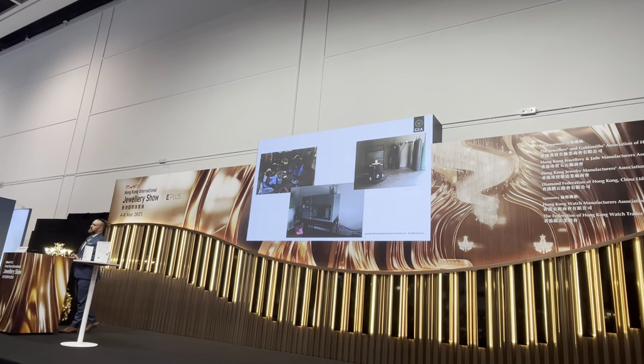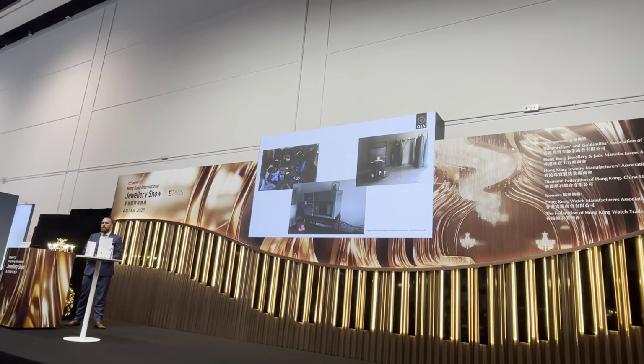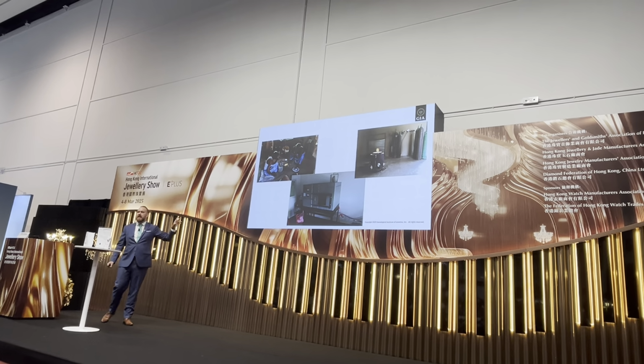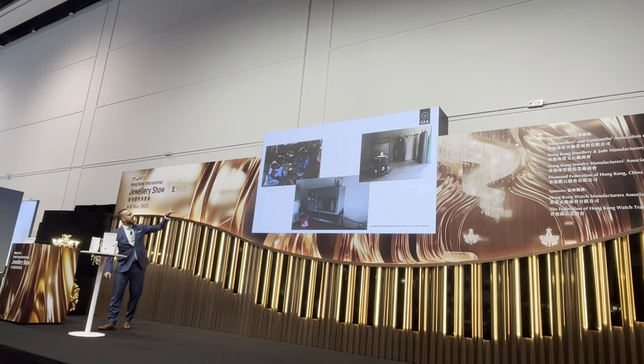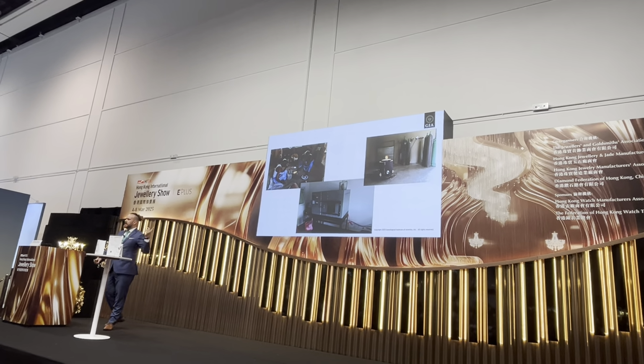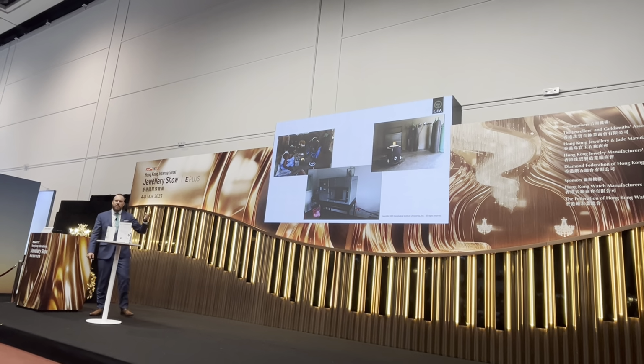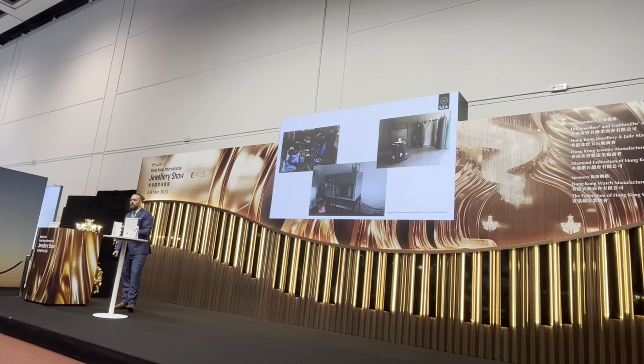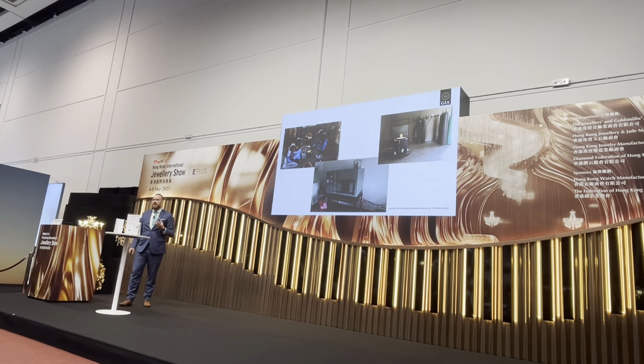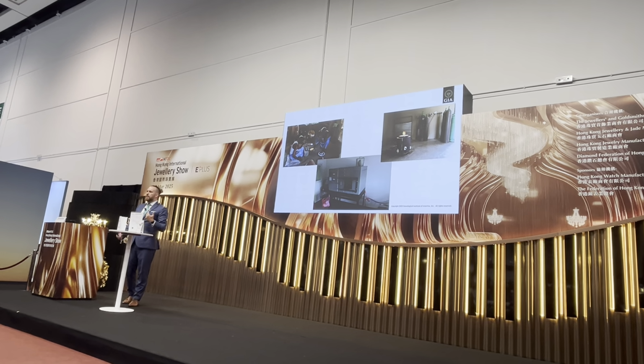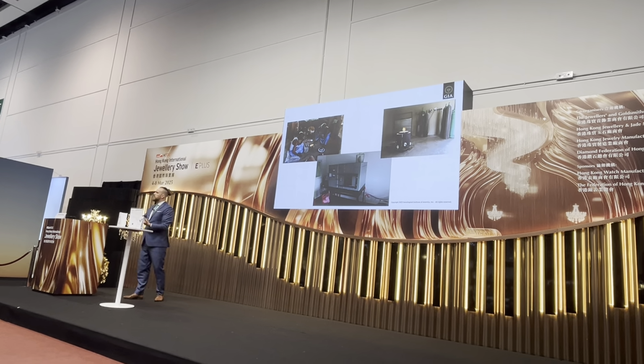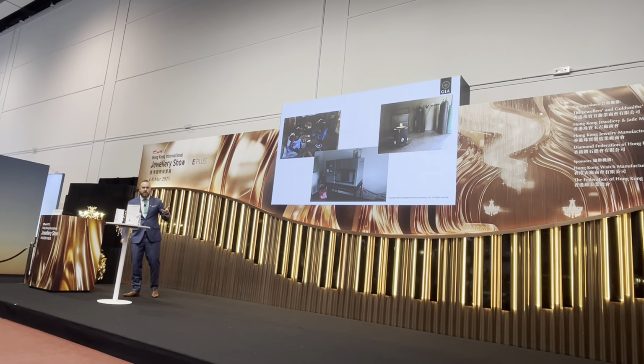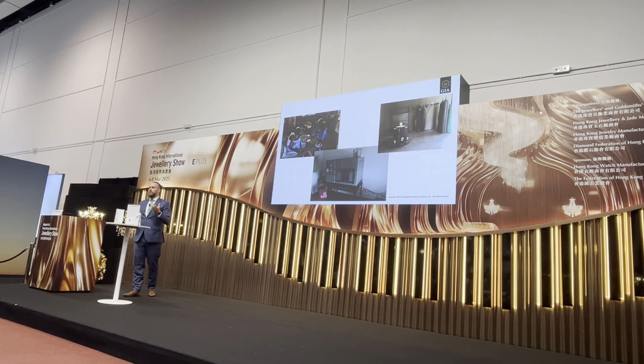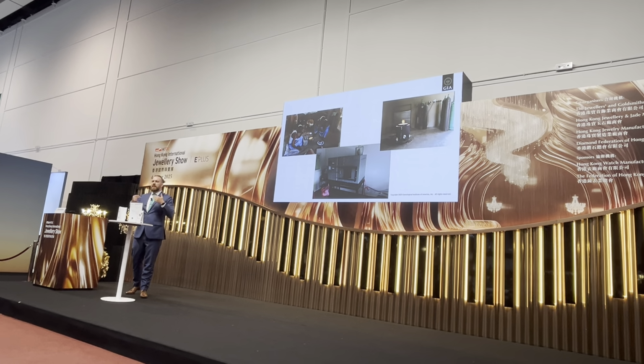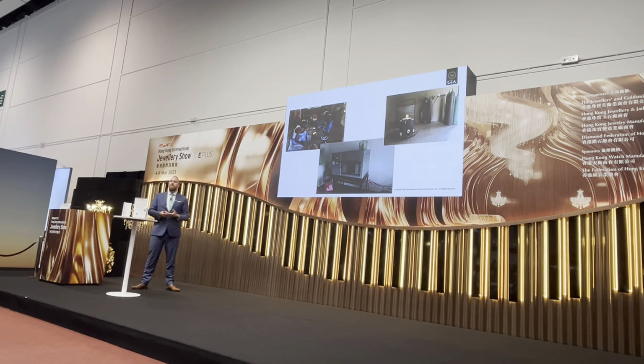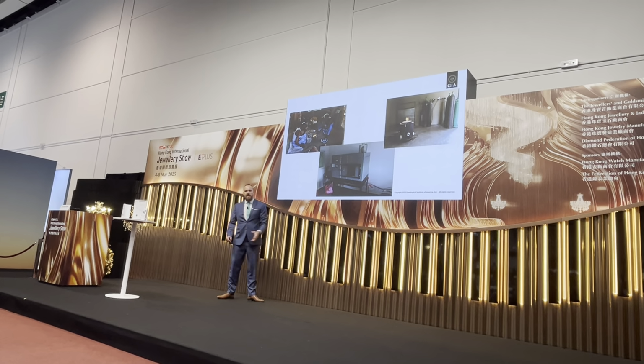Now, we can put these stones in a furnace, and heat treatment can happen in a number of different ways. So here are 3 heat treatment styles that are still occurring today, with the one on the top left being the most traditional one. This was already described more than 800 years ago, but people are still using the same technique, where they're using blowpipes and charcoal to improve the color of sapphires. Then we have the one on the top right, which started happening about 50, 60 years ago, where people are using fuels that could be diesel, kerosene, charcoal, to get a higher temperature and increase the burning temperature, getting a more drastic effect.